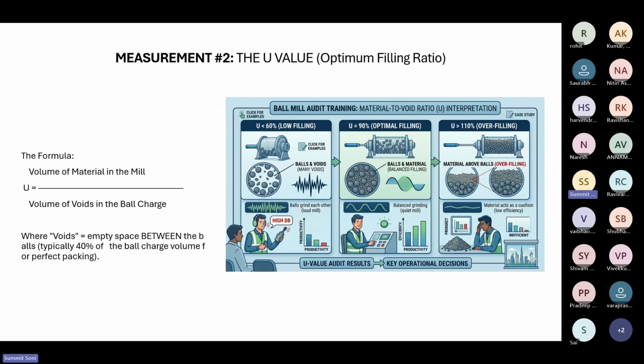The material grinding will be very fine, obviously, because it's not optimum and not sound. If it is in the middle, the U is around 90, let's say, the voids are perfectly filled. The material is between the balls and the balls are grinding the material. There's an optimal level where you will be listening to a very low rumble and it's a good sound.